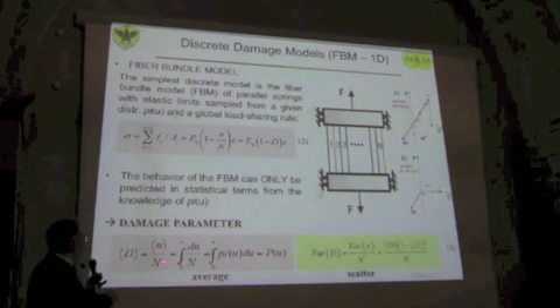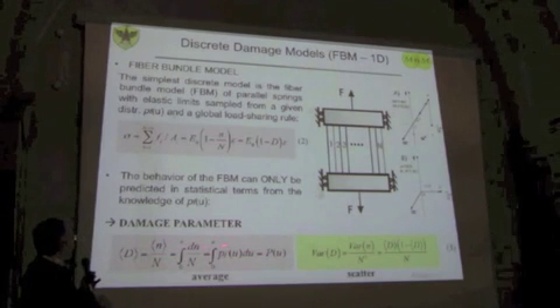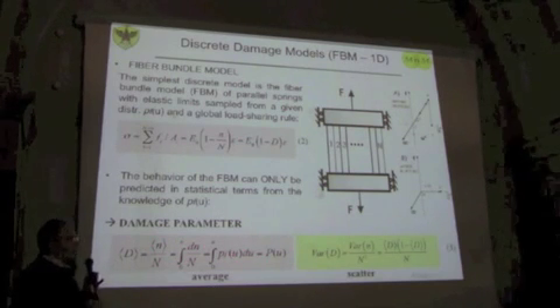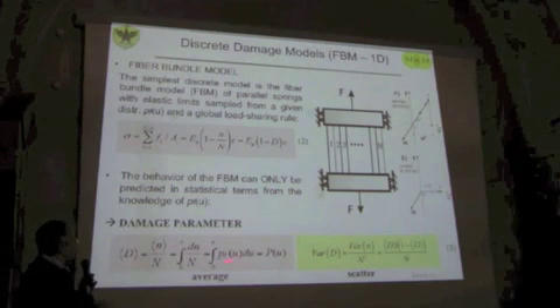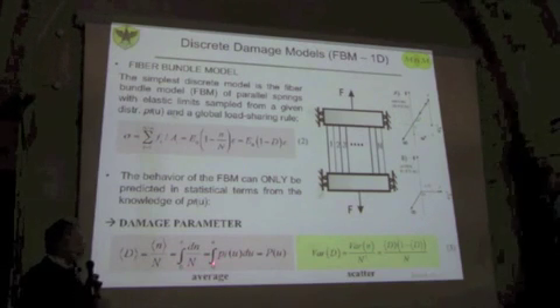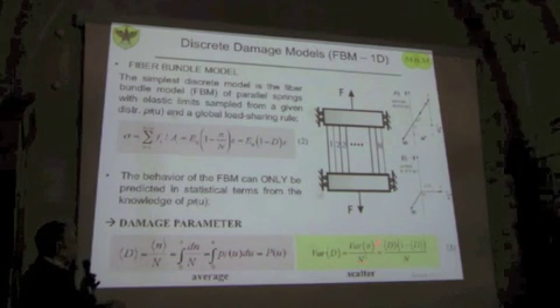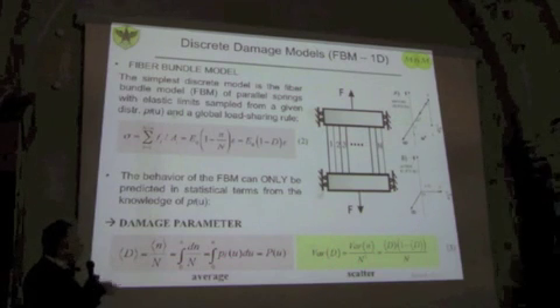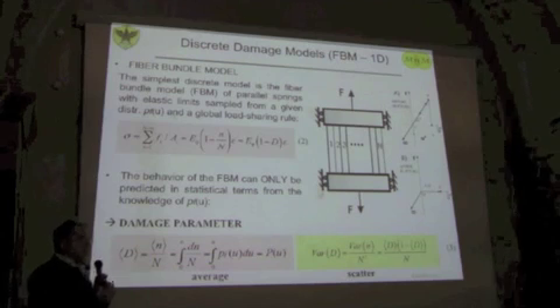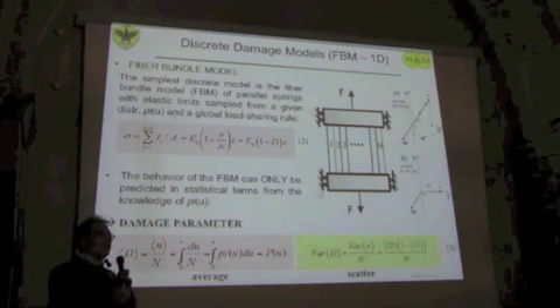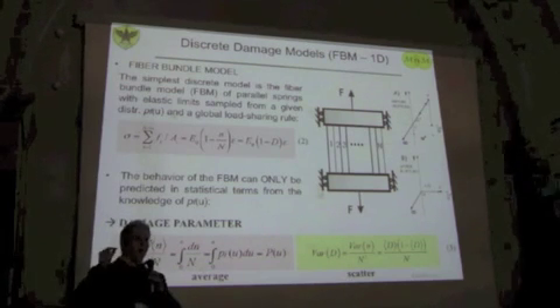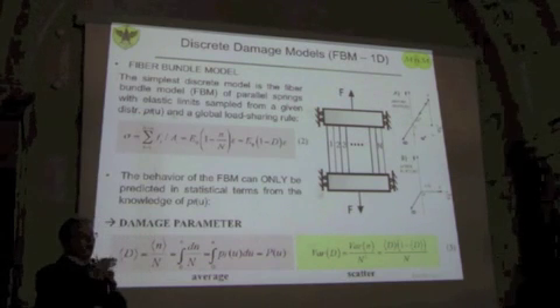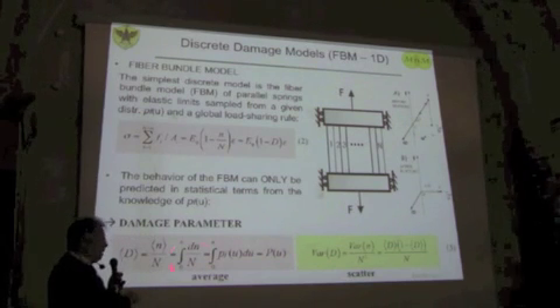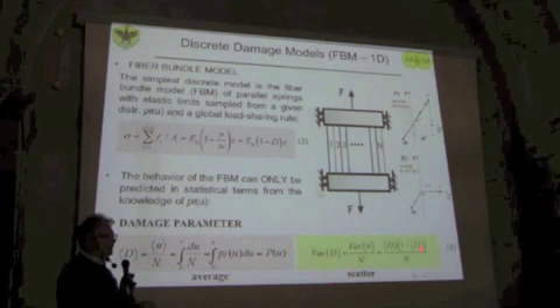Now, together with this, and of course you just sample a critical distribution for any sampling distribution, and you come up with all sorts of damage parameters simply by integration. You can also calculate the variability of the response, because this is a random model. If I have a population of critical strain, I just sample n of them, and then based on my sample I will have a certain evolution. So mean response, average, but also scatter.